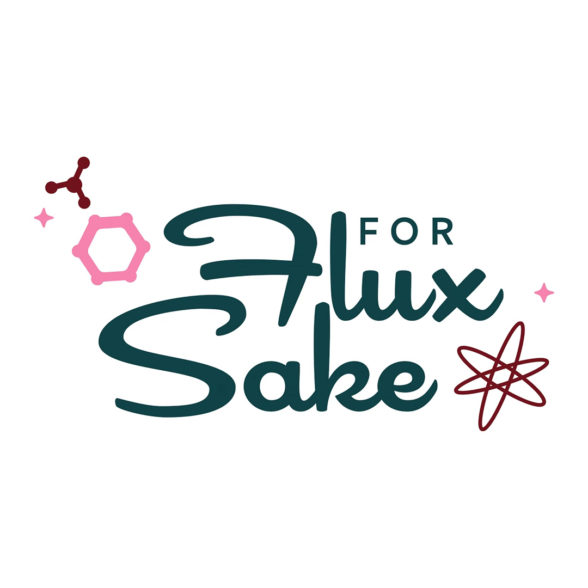The problem with crystalline glazes is that they will grow or not grow for a number of different reasons. And this is the common thing where people will see their glazes sometimes getting crystals and sometimes not getting crystals. And depending on why, it becomes a really big deal as to exactly what that crystal is or why it comes and why it goes. And that's a very, very long story. But the number one thing that you'll often see is temperature, right? One rule that we'll often talk about with crystalline glazes is if your kiln fires hotter, you will get fewer crystals. And if your kiln fires cooler, you will see more crystals.